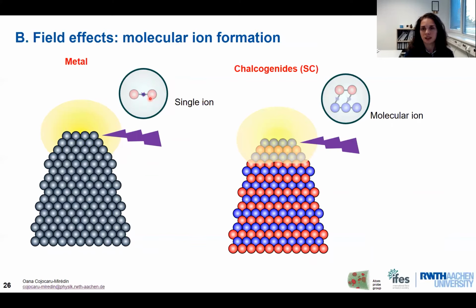And for the semiconductor materials, this is the opposite. We have seen that the field penetration depth is strongly dependent on parameters like the band gap, the dielectric constant, and the effective mass of the electrons. Of course, this also gives us a very different fraction of molecular ions, but definitely for semiconductor materials we have in general a much higher field penetration depth than the metal, and this explains why we have not always, but very often, molecular ions on the mass spectra.